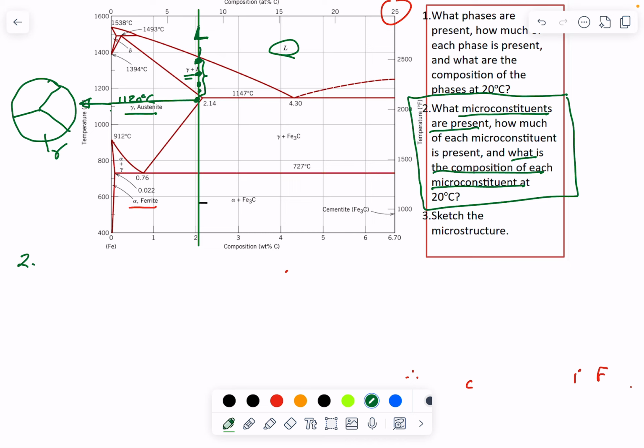All right? So what happens next as we continue to cool is that we begin to nucleate Fe3C out of the gamma. So let's imagine that Fe3C has this orange color. I'm going to associate that with the Fe3C color. And so what I'm saying is that some Fe3C begins to nucleate. Where? Well, it likes to nucleate at imperfect parts of the crystal. So it nucleates at the grain boundaries, which are certainly imperfect because it's a region where two crystals grow together.